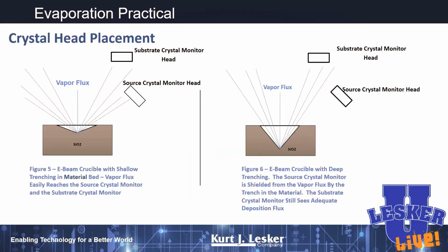Now, the position of where you put that quartz crystal microbalance is kind of critical in your system. If you're using two heads, for example, and you've got one maybe up near your substrate, which is a great location, and maybe a secondary one here, just notice that as you dig down in your material, which would be more relevant for things like E-beam, you may eventually get to where that flux is no longer impinging on that quartz crystal monitor. So be really, really mindful when you place these things in your system that they're close to your substrate, so they're going to see that vapor flux throughout the deposition.